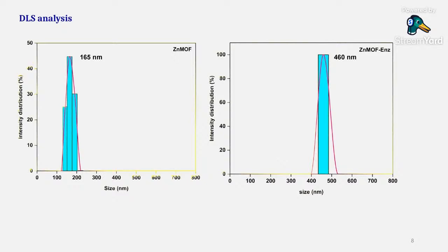In the zinc MOF, we did a light scattering experiment. What we saw was a particle size of 165 nanometers, a distributed size. Then for the zinc MOF after the enzyme coating, the size of the material increased to 460 nanometers.